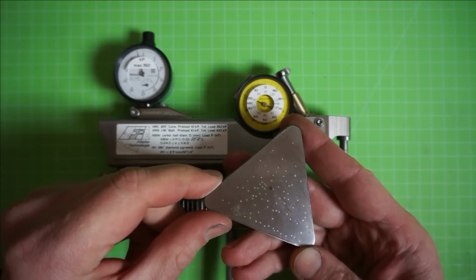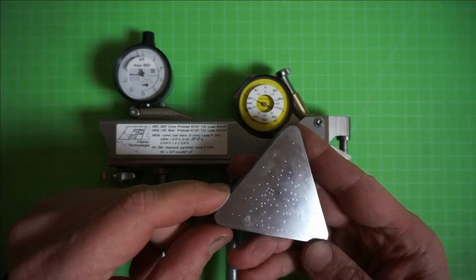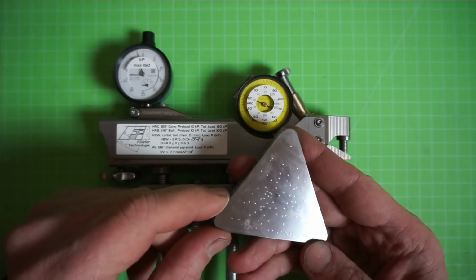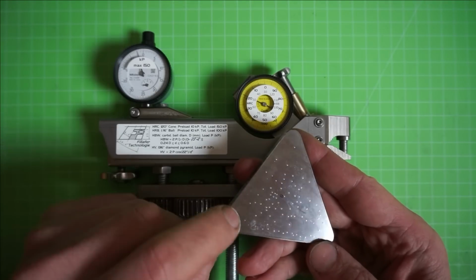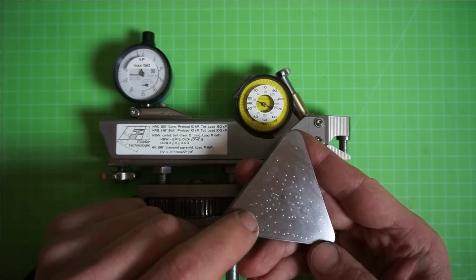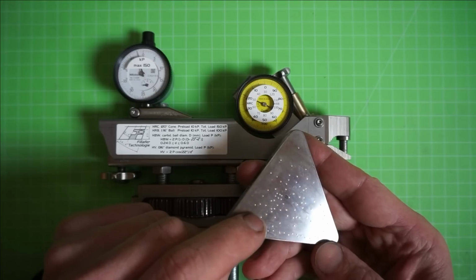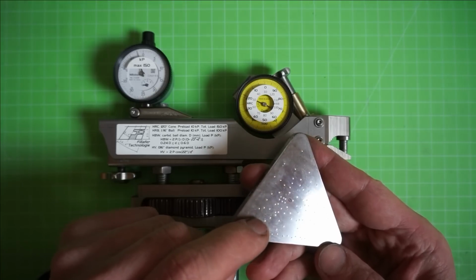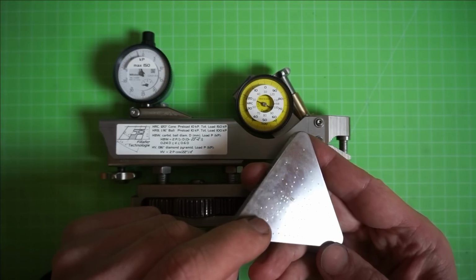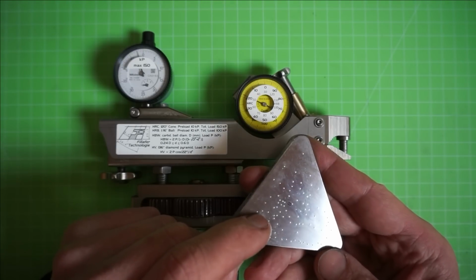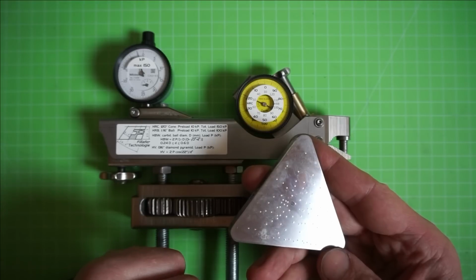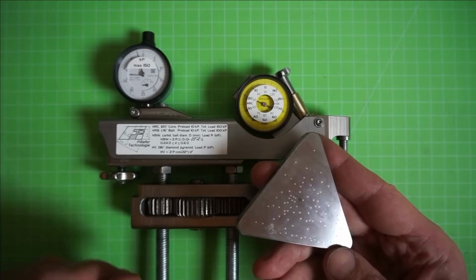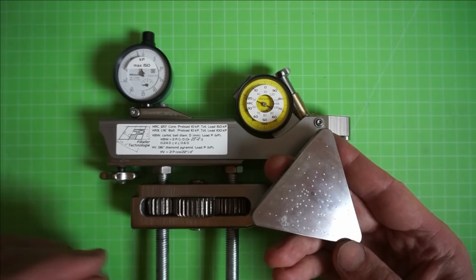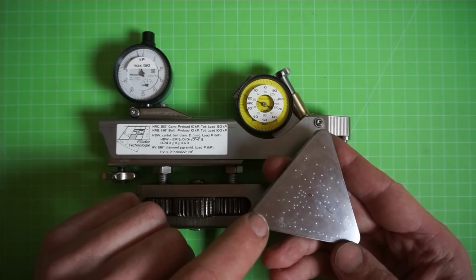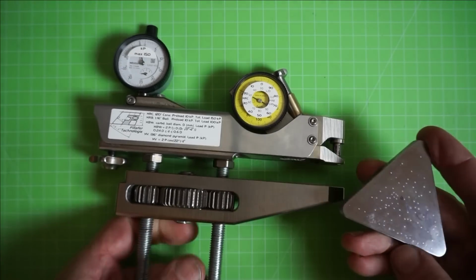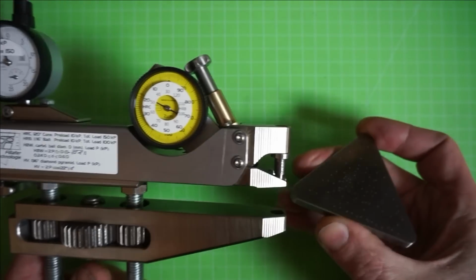Something to note here, you see I've put in already quite some indents in this test plate, or in this comparison plate. Something that's important is to stay away a certain distance from older indents so as not to be influenced by the hardening that the older indents created in the material, and only to test virgin material. So a rule of thumb says to stay away at least 5 times the diameter of the indent, and I'll try to do that.